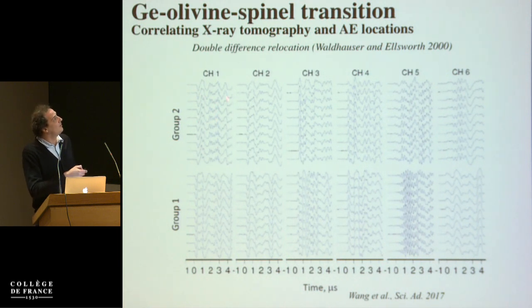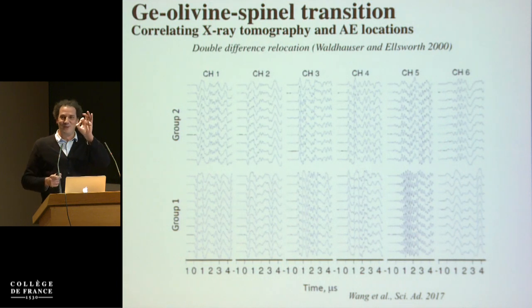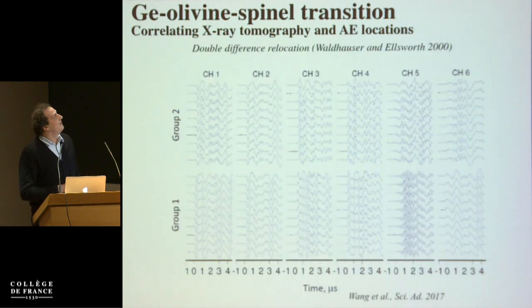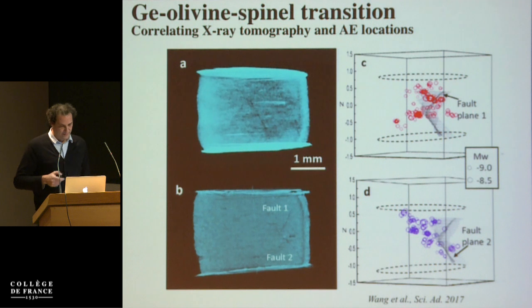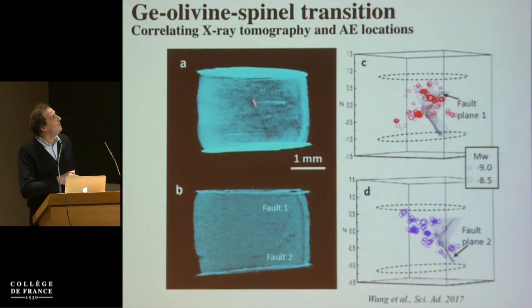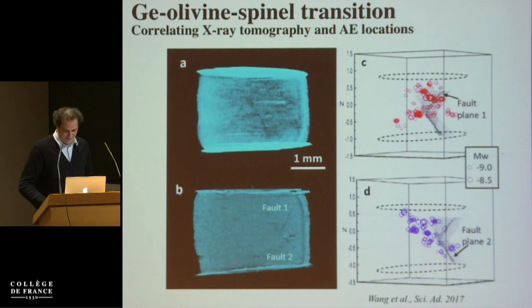So this is our 6 channels, and you see that they really look almost like repeaters, but obviously everything looks like a repeater when your sample is a millimeter cube. And so the first thing he did is he applied the double difference technique to relocate the earthquakes. And we also have the tomographic images. So this is the sample after deformation where you see the 2 faults, and you actually see the relocated faults. I want to say that this is 2 millimeters, so we have a resolution that I never thought would ever be possible, because we really seem to be able to track these faults with our acoustic emission.